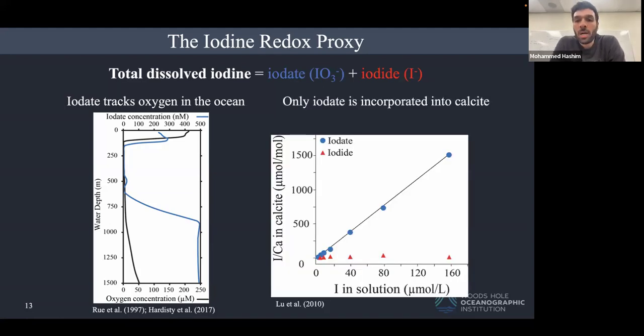In this figure, people have done experiments where they precipitated calcite. And what I am showing here are two sets of experiments. One where calcite was precipitated in the presence of iodide, the reduced form, and these are the red triangles. And the other one was in the presence of iodate. And the idea here is that when you form calcite in the presence of each one of these species, only iodate gets incorporated into calcite.